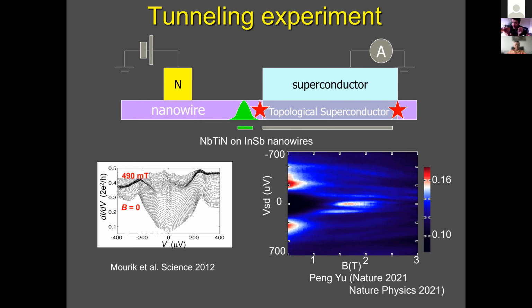And on the ends of that regime, they're expected to be these Majorana zero modes, uncoupled, and they manifest as states at zero energy, which means at Fermi level, or which means at zero source drain bias in this experiment. So if this voltage here is 0 on the battery, we should hit that level. And the way we detect it is there is a little bit extra conductance, a little more current can pass per delta voltage at zero bias. So it looks like a zero bias peak that you see here in our original data, or in this newer data. Here is a zero bias peak.